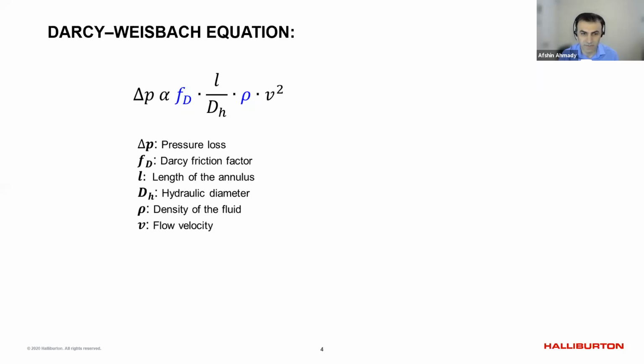And then at the end of the day, you're going to have poor cement bond and cement integrity. So velocity, it's better to not touch it. But if you have to, if you don't have time to run a simulation, the first thing we do is change the pumping rate to a lower rate to reduce the velocity and reduce the downhole pressure. But let's focus here on the friction factor and density.